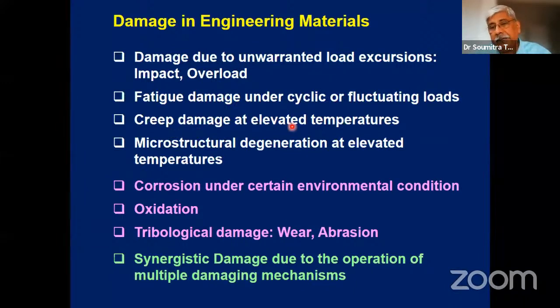It can be at elevated temperatures, creep damage. Of course, at elevated temperature, there can also be microstructural degeneration. And this microstructural degeneration can also be because of corrosion, when there are certain environmental conditions. Corrosion itself is very important on the surface, and the surface properties get lost. Oxidation, tribological damage because of wear, abrasion, all these are damaging mechanisms which are particularly prevalent on surfaces, and they have to be quantified, and only then can you tell if a component can be refurbished, repaired, and used for remanufacturing.